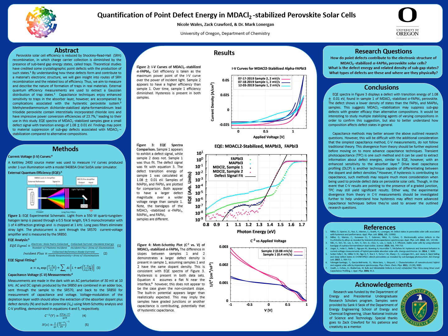Voltage modulation of the depletion layer width using capacitance voltage measurements should allow the extraction of the dopant plus defect density given as N using the Mott-Schottky equation 4. Built-in potential, VBI, can be estimated from the x-intercept of a Mott-Schottky plot. Defect locations can be determined using capacitance voltage profiling, which is given in equation 5.